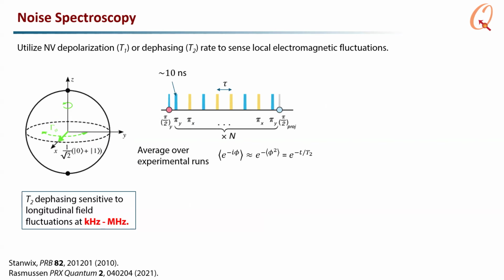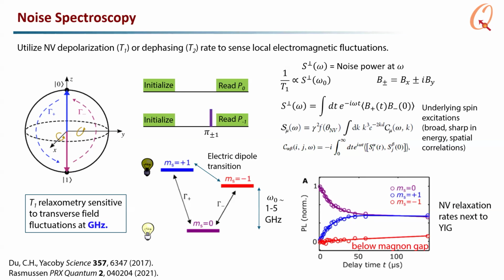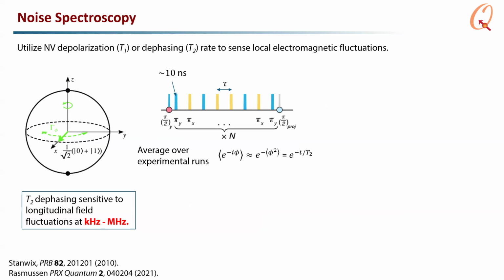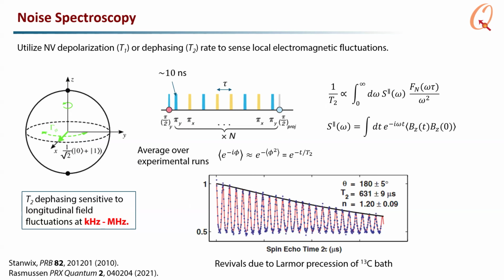So this effect also happens not only in the depolarization but also in dephasing. Whereas in T1 relaxometry we were sensitive to noise at gigahertz frequencies due to the energy separation between the m sub s equals ±1 and 0 states, for this effect we're measuring dephasing. We can tune what frequency we are sensitive to by changing the delay between our pi pulses. So the filter function I was talking about, you can deliberately change where it is centered by the spacing of your pi pulses. And because each pi pulse is around 10 nanoseconds, we're really accessing noise dynamics at kilohertz to megahertz frequencies. So you can see we're just measuring the decay envelope of the coherence of the NV center.